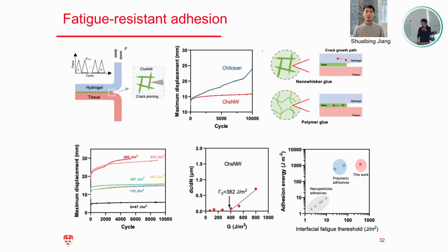And we are particularly impressed by this value because compared to what people have achieved in the literature, the threshold of other polymeric-based adhesives is only around 30 joule per meter square. So we get one order of magnitude higher compared to what people have achieved in the field.